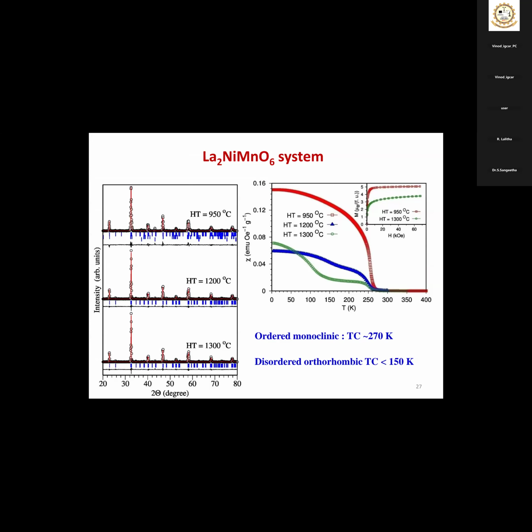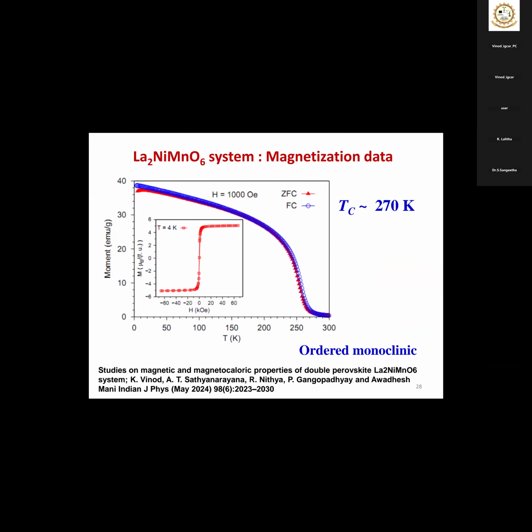If you do the synthesis at a relatively lower temperature, ordering is favored, but then the reaction completeness is also a problem. So this is the result. Ordered, low temperature synthesis means it will be ordered monoclinic. Magnetic transition will be around 270 Kelvin. That only we will concentrate on further. The ordered monoclinic around 270 Kelvin is ferromagnetic.